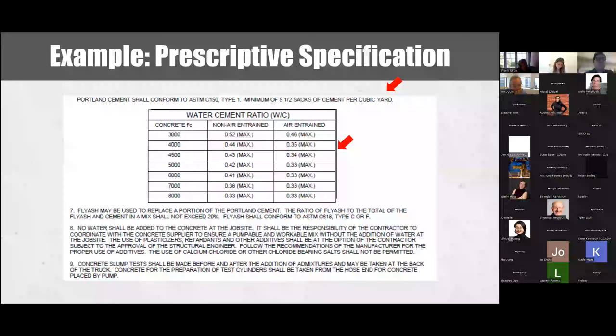More fly ash may be needed for ASR or sulfate resistance. It has restrictions on water addition and a requirement that slump should be tested before adding admixtures. This is an unreasonable requirement and unsure as to how this can be accomplished.